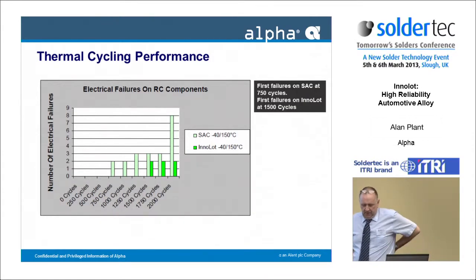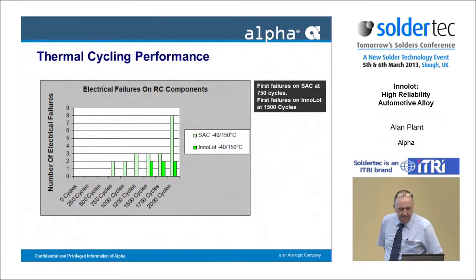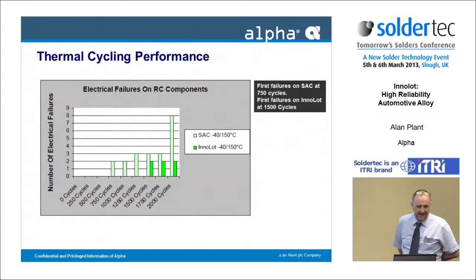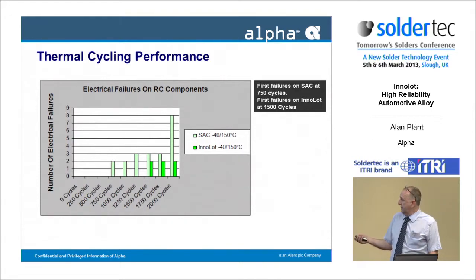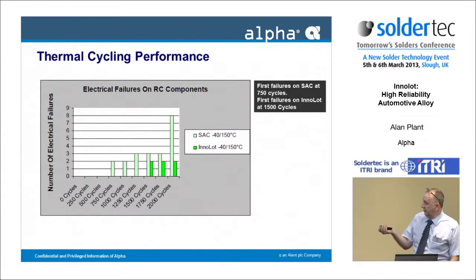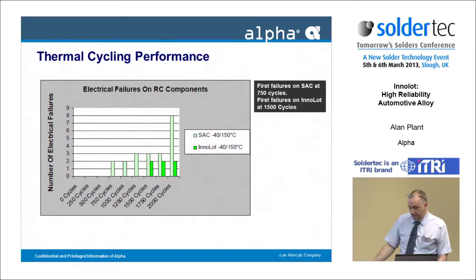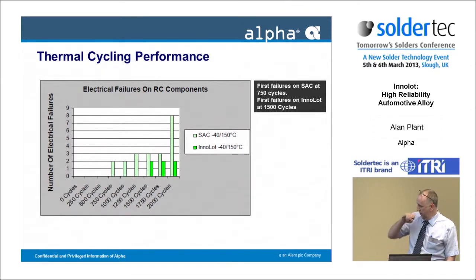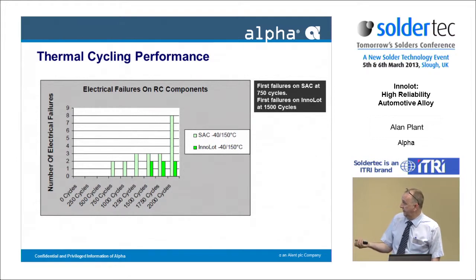Okay, so we've got an alloy. We've done something to make it mechanically stronger. It looks as though we can use it from an applications point of view, from wetting. Has it achieved the final target, that is, has it strengthened the alloy in terms of thermal cycling? So here we have the base alloy, the Innolot, here, the SAC alloy there, -40 to 150 thermal cycling in groups of 250 cycles. This is on resistor and capacitor components, so there are no compliant leads. These components, in this particular case, tended to show first failures in the end user environment, and we can see a clear shift in that the Innolot are not showing the initial failures anywhere near as soon as the standard SAC alloy.